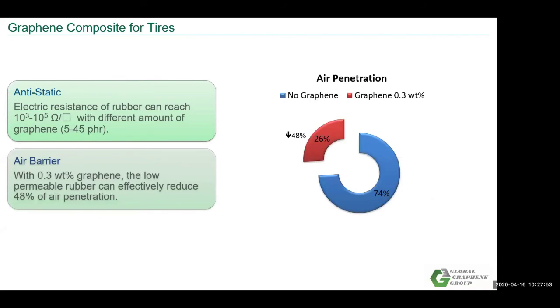In addition to that, as I mentioned, it can offer improvements on the anti-static performances. So we can reduce the electric resistance of rubber down to 10 to the 3 to 10 to the 5th ohm per square with different amounts of graphene. And also with only 0.3% of graphene, we can see very low permeability of the air. It can effectively reduce 48% of air penetration, which is very significant.